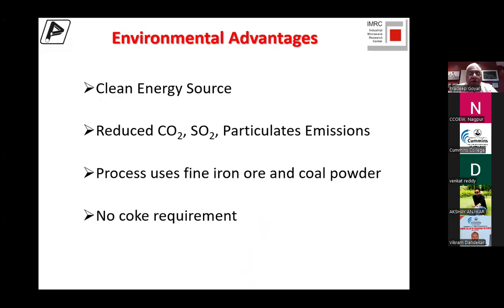Again, clean energy source, reduced CO2, SO2, because we are using here only a stoichiometric amount of carbon in the form of coal. Normally people use double the amount of carbon because some of it goes to heating the material and some of it goes for reduction. Here no carbon is required for heating, only for reduction. So theoretically, we can do away with 50% carbon compared to the regular iron making processes.